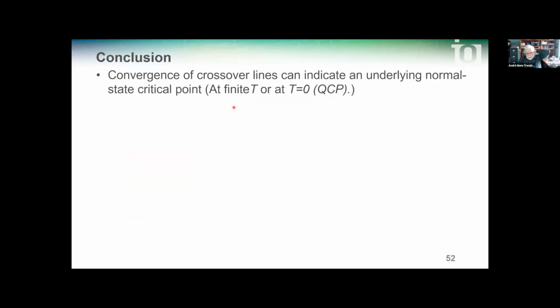So, in conclusion, I discussed that the convergence of crossover lines can indicate an underlying normal state critical point, either at finite temperature or at zero temperature. I introduced this concept of a Frenkel line. Contrary to thermodynamics, where we have some RG, here I don't know about the universality class of this in dynamics. Also, we tried to make connection with experiments, but it turns out that all those that we found had a lot of phonons at low frequency, and then doing a Fourier transform became a nightmare.